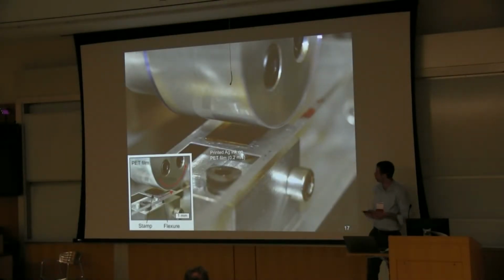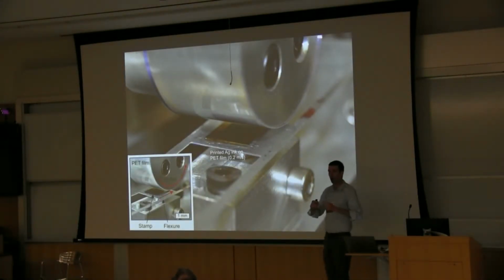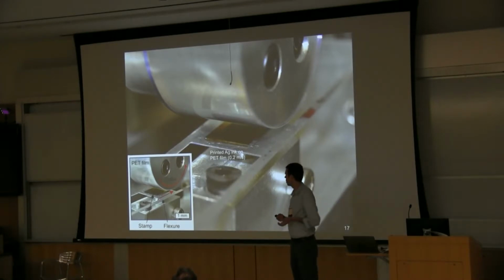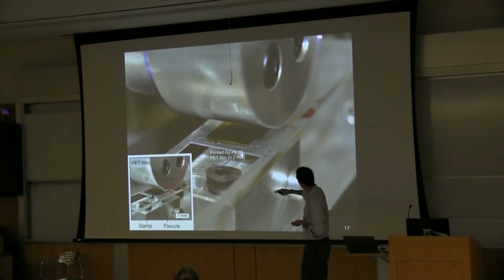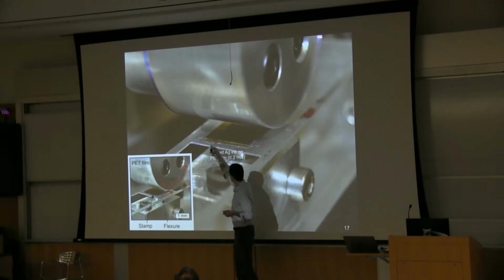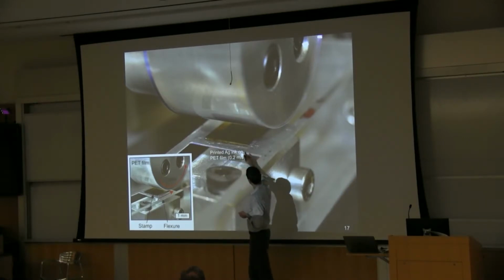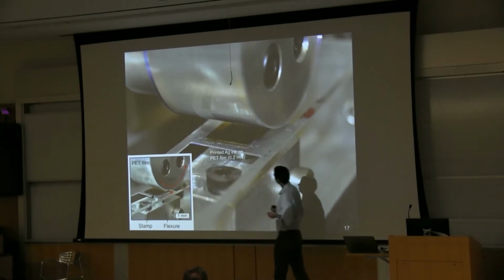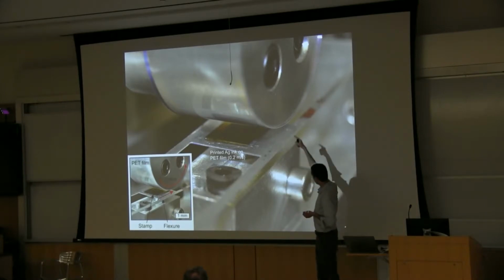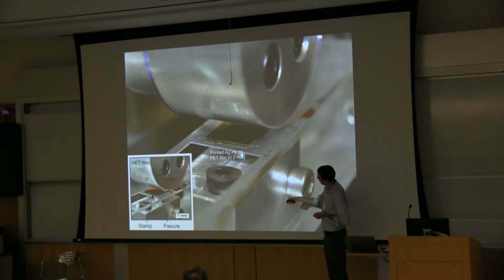The last thing I'll show you is a simple example of the possibility of scale up. So we wanted to start to study the mechanics of this as a continuous process. So we built what we call a plate-to-roll printing system, where here is the stamp, roughly a 1 by 1 centimeter silicon wafer with a pattern of CNTs on it. And this is a roller with a polymer film on the surface. And our little machine basically executes coordinated rotary and linear motion.